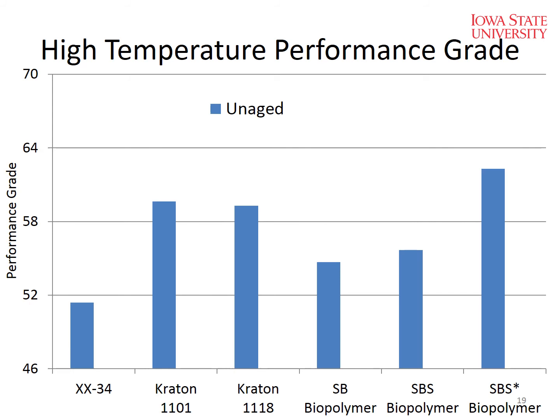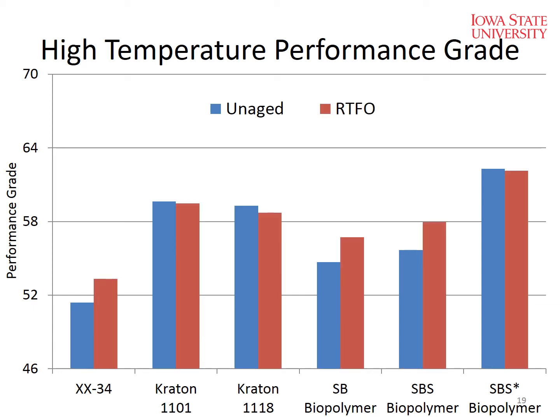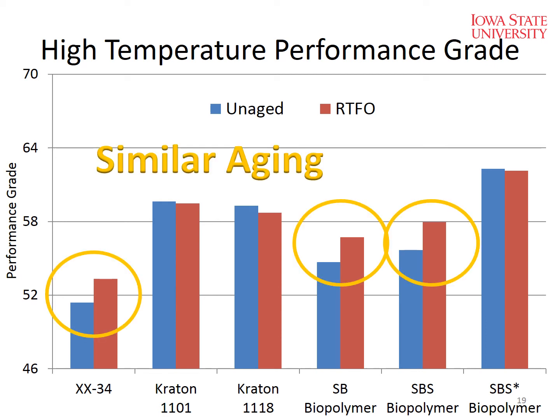So when we go in here, and this is from work from a year and a half or so ago, we can benchmark to the 1101, 1118, and then we can look at the diblock versus the triblocks, and then we can see what we did is we reacted this out at a higher temperature, and that's what produced the better performance grade for us there. Okay, so reaction temperature matters basically. This is what it shows in the RTFO, and it further highlights the fact that with the diblock and the triblock, if we run these out at higher temperatures and blending, after RTFO there was some more chemistry occurring, and that's what we see here. So we have some similar aging going on there.